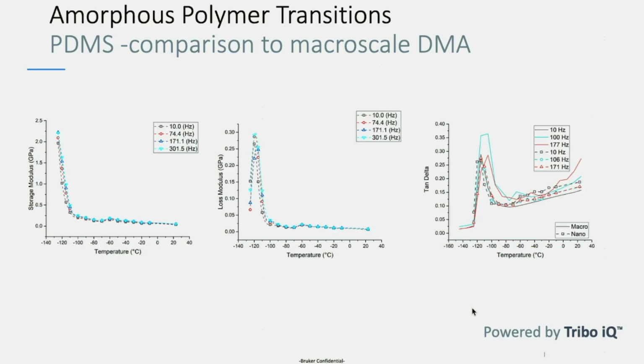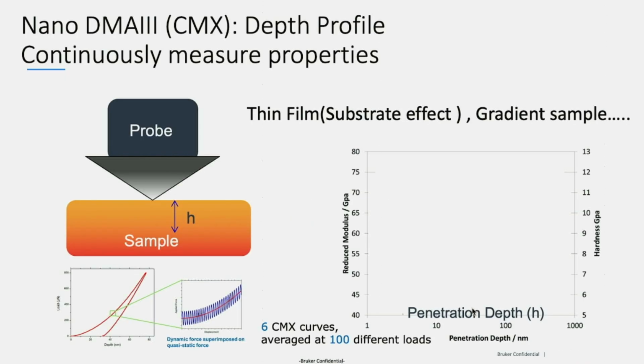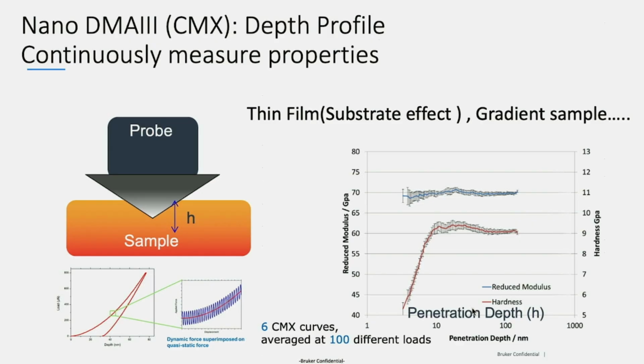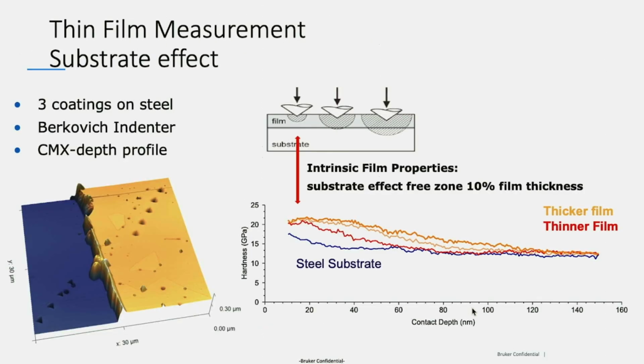This is a PDMS. We can also cool down our temperature to minus 100, minus 120 with liquid nitrogen. So you can see the Tg. For some polymers, the Tg is below room temperature. Nowadays, the nano indenter can still help you understand the mechanical properties at different temperatures. And for thin films, we can measure with continuous measurement. I will go through this in detail in my next session to avoid the substrate effect, right?